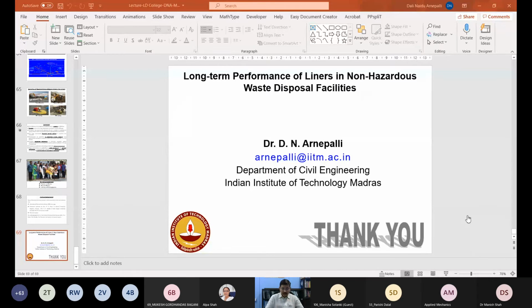Yes, I think we have conducted a wide variety of leachate compositions also as a part of that study what I have shown earlier. The aging to a certain extent depends on physical parameters like overburden loading, temperature, and chemical loading. There is no doubt. So what we have seen is the service life is really going to change the moment we change any one of these parameters. But in general, rather than worrying about the composition change in the waste, what I would recommend is you focus more, while selecting the material, on their chemical properties, and the interaction compatibility between the waste and the liner. That's really going to give you the long-term performance.